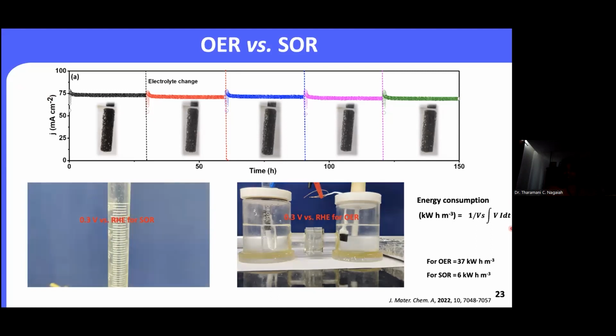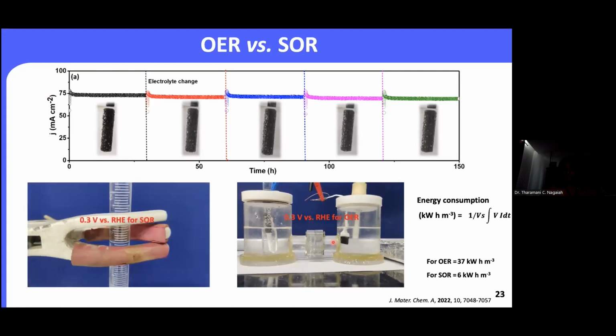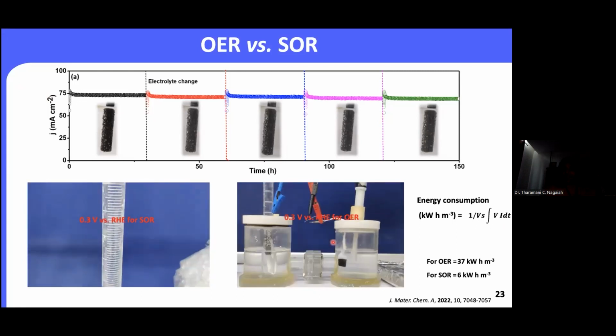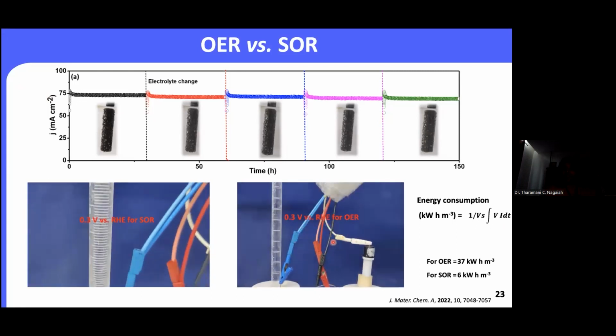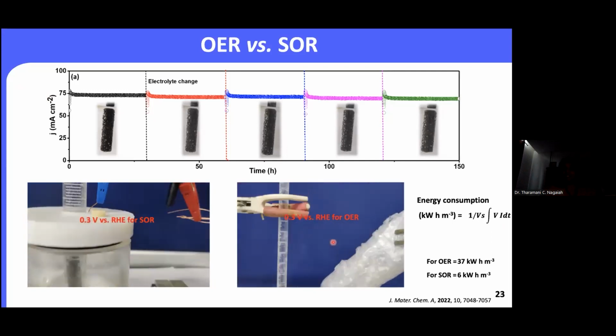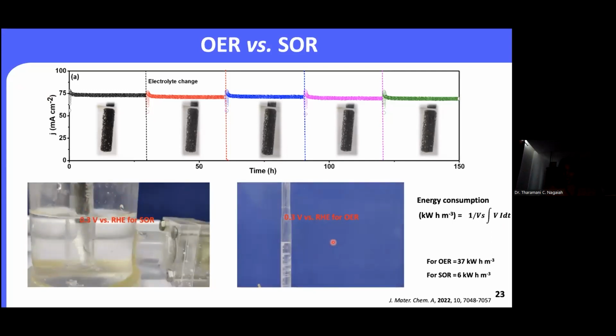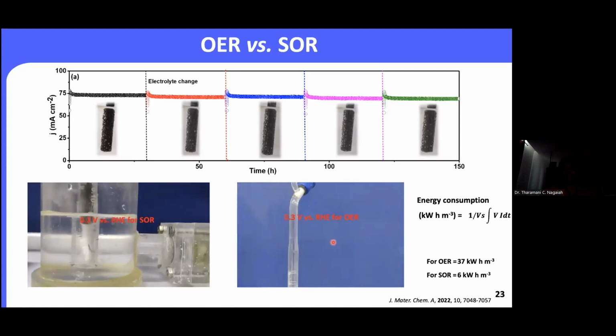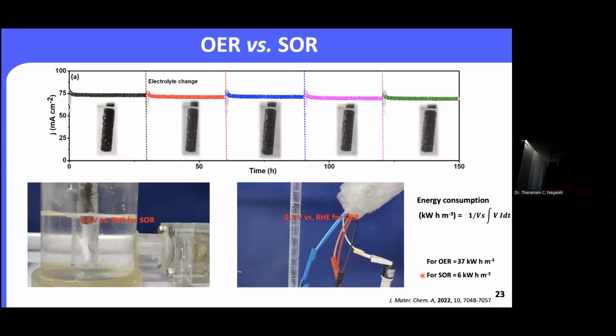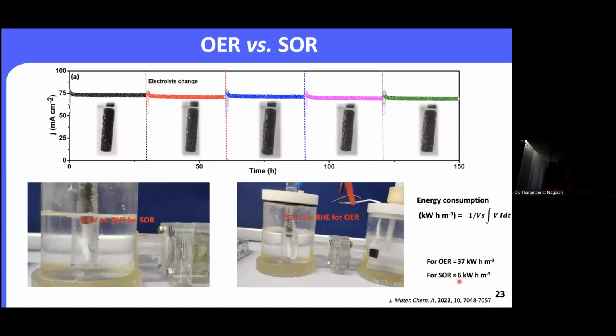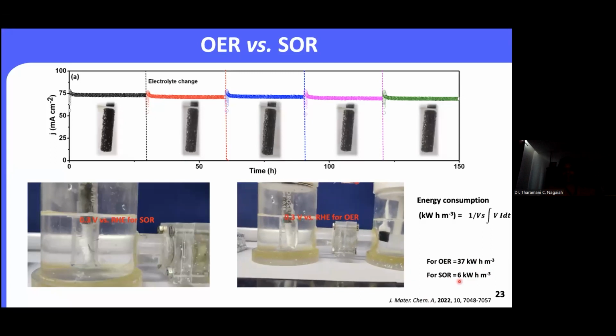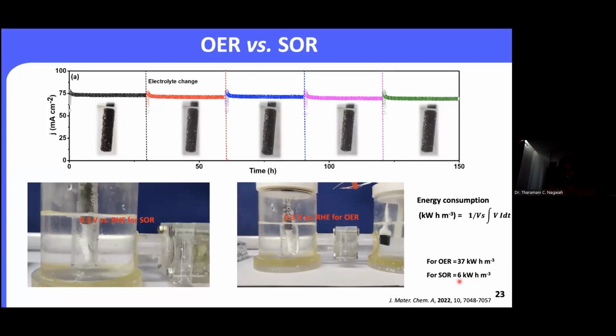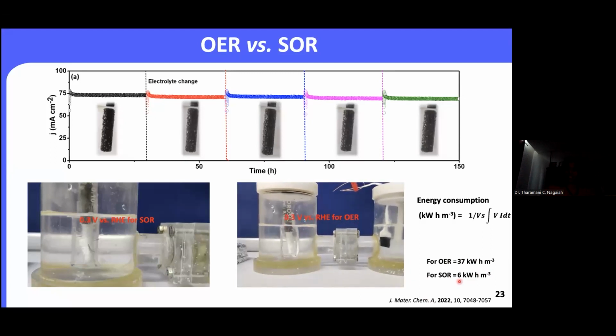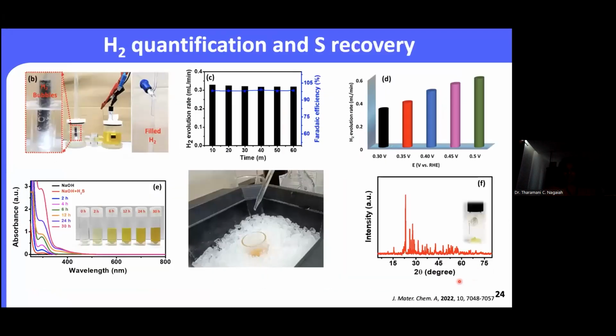When it comes to water splitting here, in the absence of HTS, at 0.3 volts, we did not see any bubbles at all. So that means we are not splitting the water at all at this potential. This potential is not enough to split the water to produce hydrogen. When we calculate the energy consumption for the oxygen evolution reaction, we need about 37 kilowatt hour per meter cube. And when you compare with the sulfur oxidation reaction, it's almost 6 times. This is what we predicted before starting this experiment.